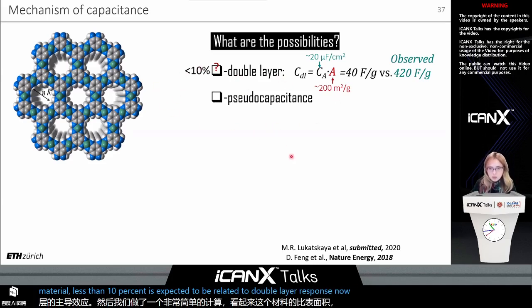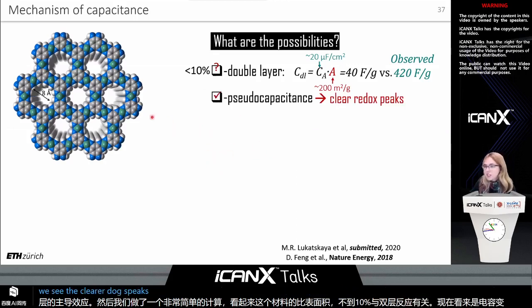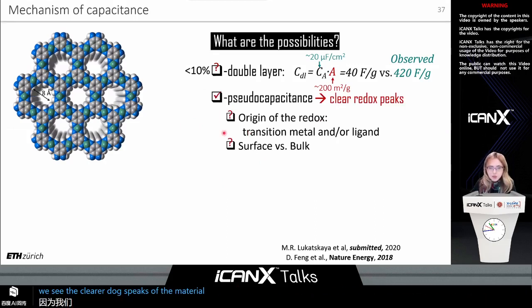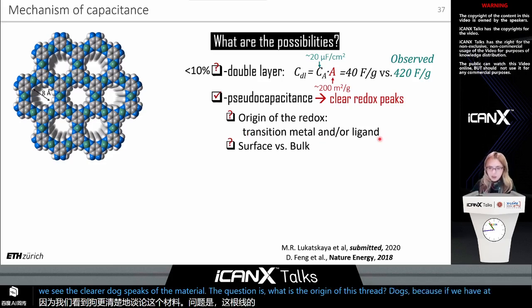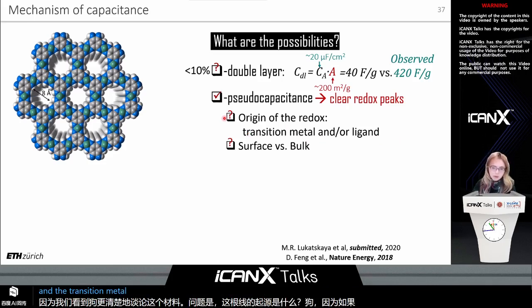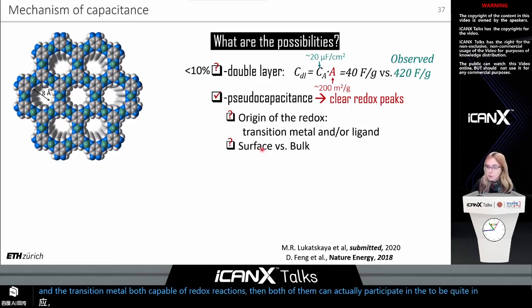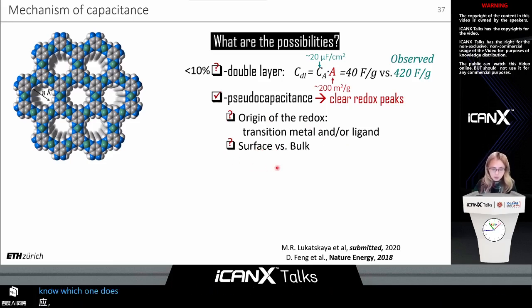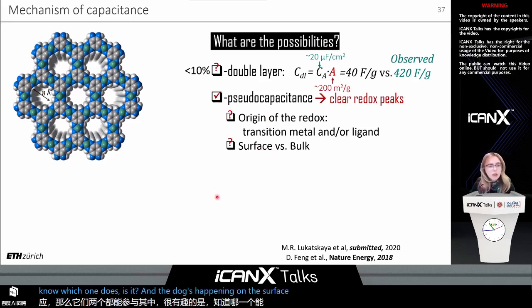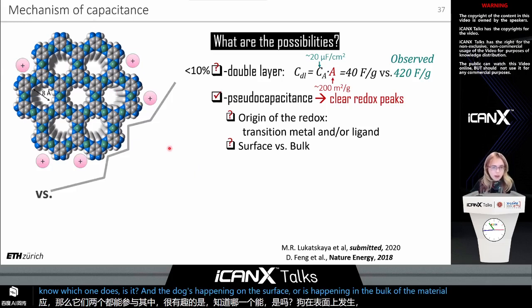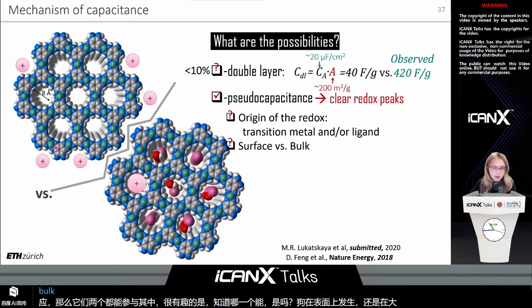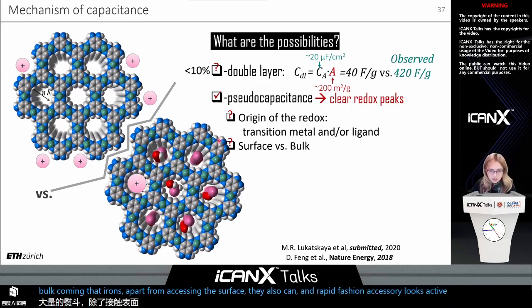Now, it seems like it is the pseudocapacitance because we see the clear redox peaks of the material, but the question is, what is the origin of this redox? Because if we have the ligand and the transition metal both capable of redox reactions, then both of them can actually participate, and it would be quite interesting to know which one does. Is it redox happening on the surface, or is it happening in the bulk of the material? And in this case, by bulk, I mean that ions, apart from accessing the surface, also can, in rapid fashion, access redox-active sites inside the particle.